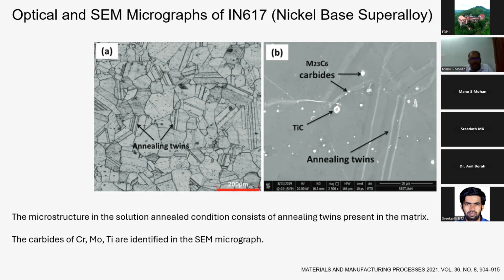So now this optical microscope will simply give me annealing twins - I will come into twin characterization later. It just gives me twins, but further to that I am not able to gather any information. So to gather the information, I have to do the EDS, the energy dispersive spectroscopy, which clearly gives me what elements are present in it. So these are annealing twins - we will discuss about twins later.